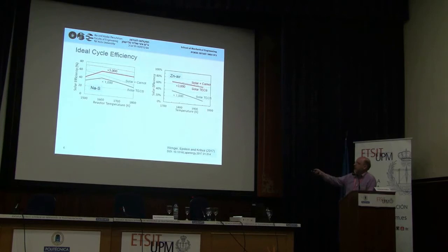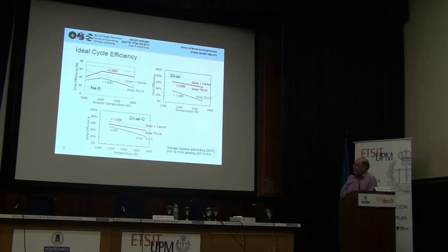And here comes the ultra-high temperature. This requires a temperature of more than 1,600 degrees, so this is not easy to do. The same analysis for zinc air system. Again, if we have the concentration that is high enough, we can reach more than 60% overall conversion. Again, I remind you, this is an ideal system, not yet with realistic losses, but this again requires very high temperature. And this is the other variation.